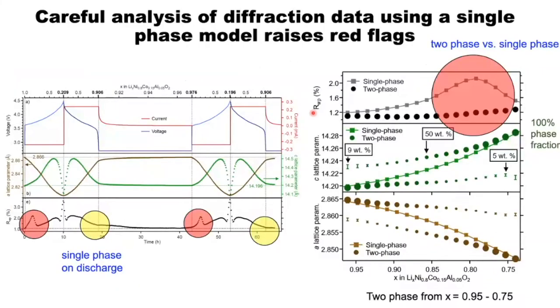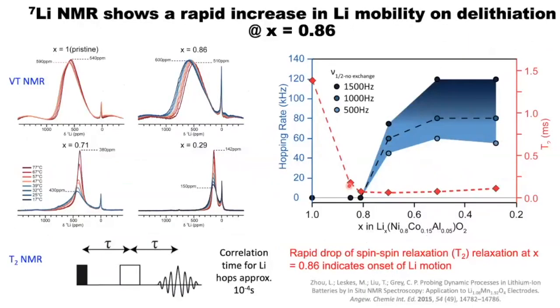So what Antonin did was then to move beyond the single-phase analysis to fit the first process with the two-phase reaction. And so what you're seeing here is the C parameters and the A parameters changing with the two phases growing in. So you have a second phase with a larger C parameter, which gradually grows in percentage. And by the time you're at 0.75, that corresponds essentially to the full phase fraction, while the initial material dies. So is there a role for mobility in this? There must be, otherwise I wouldn't be linking the two stories together.